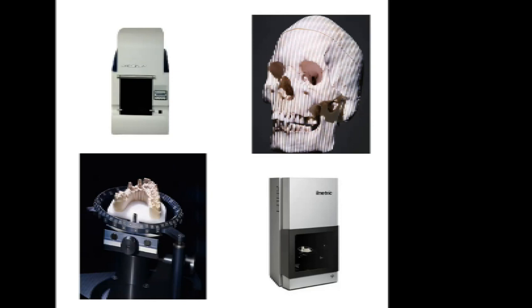Typically, desktop scanners now are sub 10 micron, typically 5 to 10 micron accuracy. And when you think about the accuracy of the original recording of the impression, that probably wasn't accurate to more than 5 to 10 micron, I would hazard a guess, probably more like 20, 25 micron. And then, of course, when the model was cast, that was another slight degradation in accuracy and other measurement uncertainty from the casting process itself. So when we've got scanners that are capable of scanning at 5 micron, 10 micron, they're more than accurate enough to do the job.